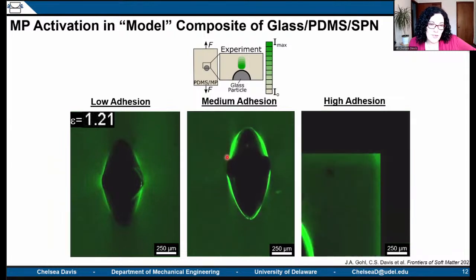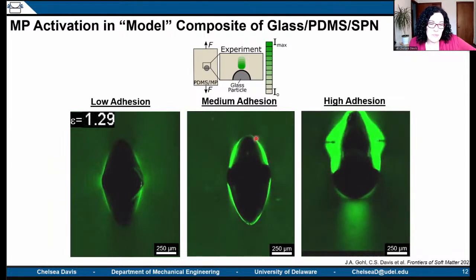But what's more interesting for us was we observed really interesting Gent-Park debonding or Gent-Park cavitation that occurs when you have a weak-ish interface that holds for a while, stores a lot of mechanical energy, and then leads to a large-scale cavitation event. So this you can think of as like a hollow Easter egg that has opened up at the top and bottom of our particle. And I don't know if I can play these again.